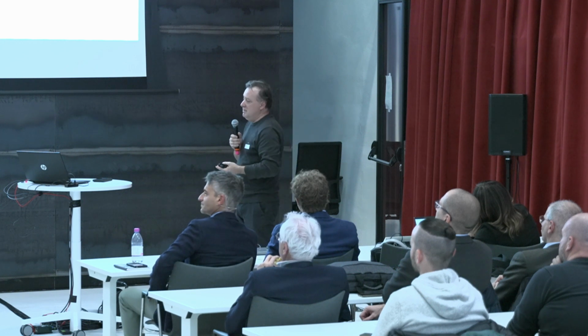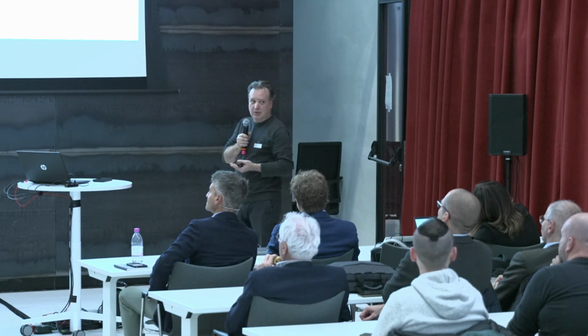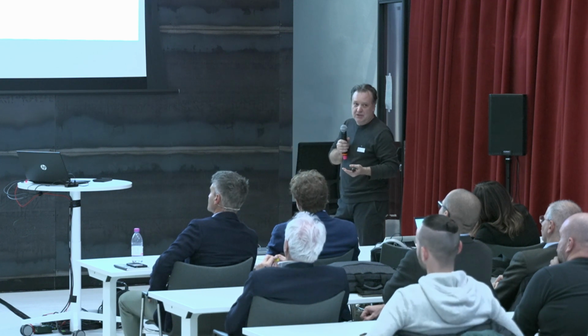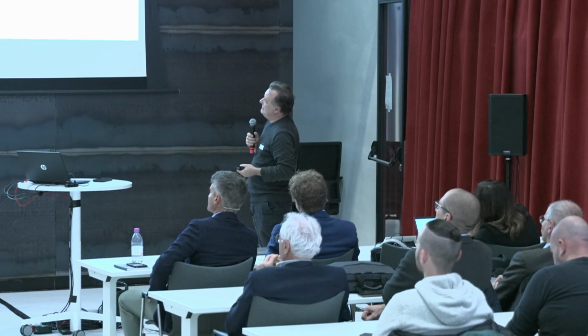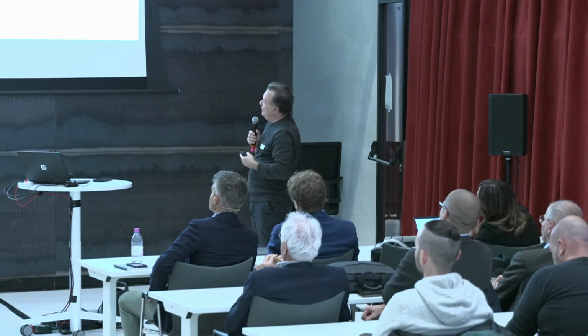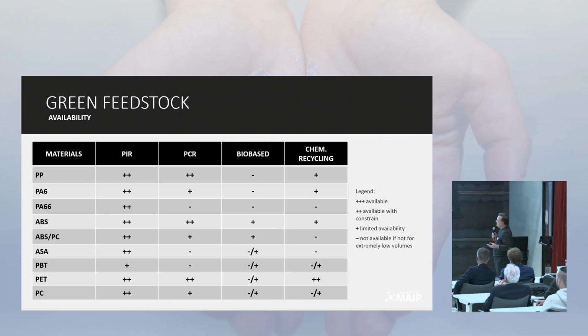So we can maybe make a business case granting post-consumption, but if you look at big volumes, today we have to consider post-industrial at the same level as post-consumption, otherwise we will have a big problem satisfying the requirements. There are other materials for which you have almost all solutions, like ABS, where there are already bio-based or partially bio-based solutions, and you have chemical recycling. The same is for polyester. The polyester world is one of the easiest in terms of chemistry, where you can have all solutions: post-industrial, post-consumption, bio-based, and chemical recycling too.